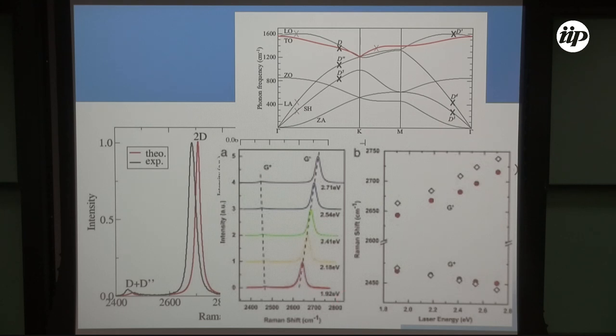So this is an experimental paper, and now it's very easy, because when you have your cone, if you change the laser energy, you are now exciting electron-hole pairs in different points of the cone, and then you are scattering with different values of phonons with different values of wave vector. So this will change the frequency you are measuring.